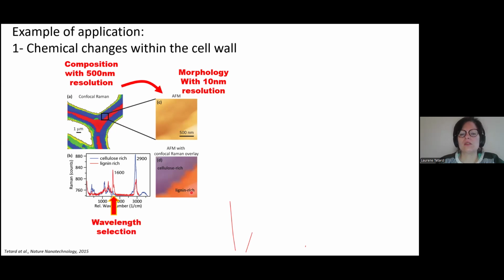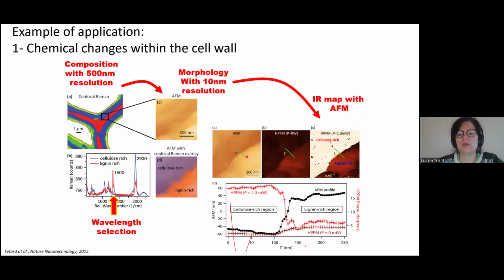And so what the AFM-IR allowed us to do is, in the same region, to get the morphology image and then to excite the cellulose band in the system, with the wavelength we're choosing that is meant to excite cellulose. Oh, that was for lignin, but the image is for cellulose. Then we can have a region where only one of the regions responds, the region on the top left. So that showed us that we can explore the plant cell wall and start getting some information about cellulose and lignin.